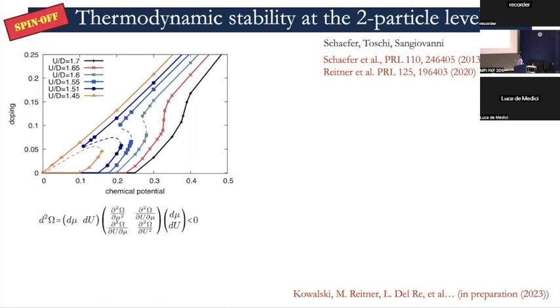And the reality is that we have a space of parameters here, which is u and mu, and the condition of stability is embodied by the fact that the Hessian of the relevant thermodynamic potential has to be negative definite, which turns into a condition on the principal minors of this Hessian matrix. So the first minor is actually d²Ω/dμ², so it's minus the compressibility. So the compressibility has to be positive, and we know this.